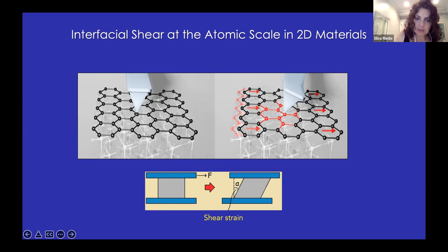But the tip is still in contact with the graphene film, and underneath we have the silicon carbide structure or another type of structure that I will talk about in a moment. And then we slide a very small amount, and we stay in the elastic regime. In this way, we measure what we call the interfacial shear modulus of the top atomic layer with respect to everything that you have underneath.